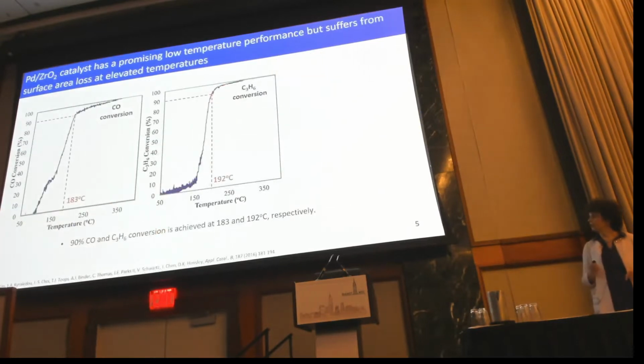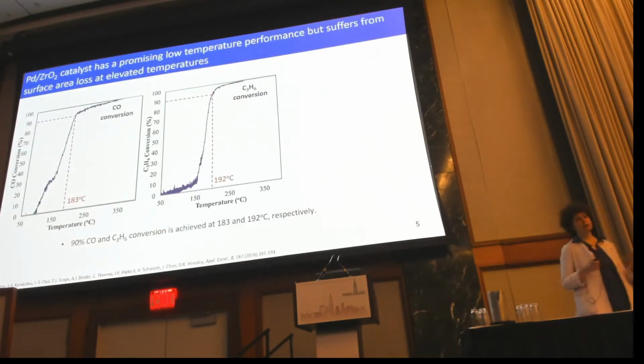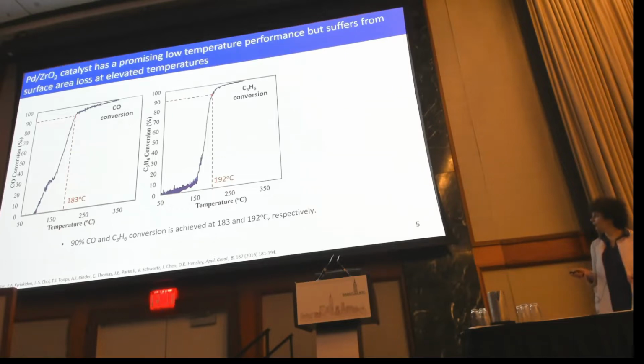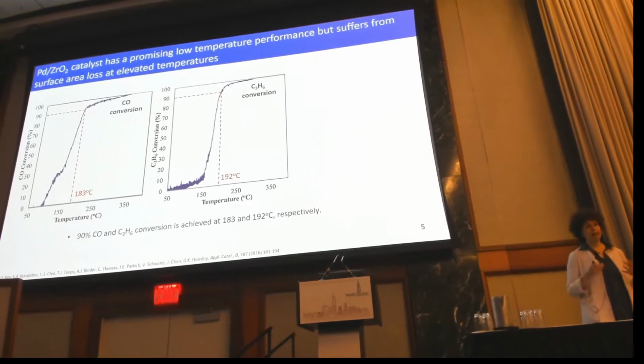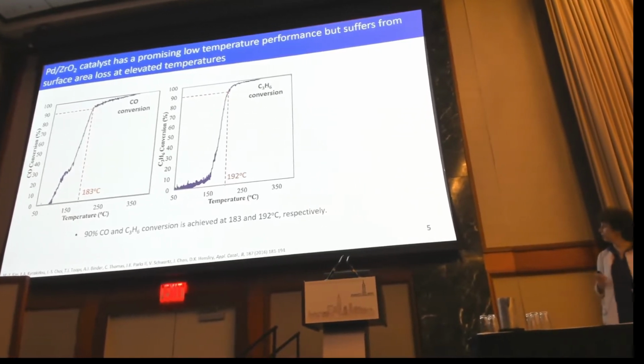However, looking into the literature, we found that palladium on zirconia seems to have improved low temperature performance. And here we can see the CO conversion as a function of temperature and the propylene conversion as a function of temperature for the palladium on zirconia. So what we see is that this catalyst achieves 90% conversion of CO at around 183 degrees C and 90% conversion of propylene at around 192 degrees C. Still not close to the 150 degrees C target, but it seems to be a promising material.